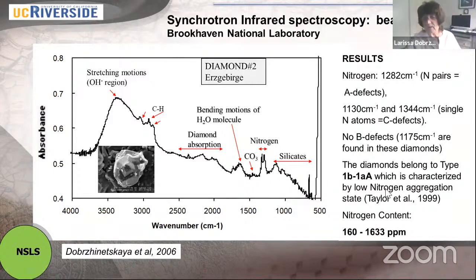So the diamonds from ultra-high pressure terrain contain so-called C defect and A defect, but they do not contain B defect. So they belong to group 1B1AA, which characterizes a very low nitrogen aggregation. What does it mean? It means that this diamond did not have a long residence time inside of the Earth in that depth where the diamond was formed.